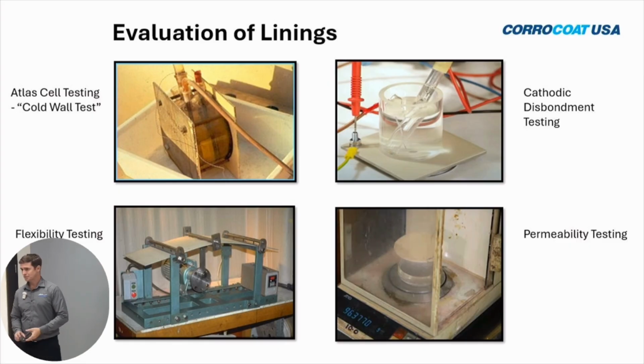Cathodic disbondment testing. This tests the electrical insulation value of the coating. The coatings are insulative. At 40 mils, this product, Polyglass VEF, is resistant at 25 kV, so 25,000 volts. The idea is if you know how resistant something is to electricity, then you'll know how corrosion resistant it is. We like this test, and it's one of the first tests when we're testing coatings for efficacy because you can have a quick feedback loop. Yeah, you don't have to wait 6 months like this test. You can go through and fine-tune that this mixture works better than that mixture.